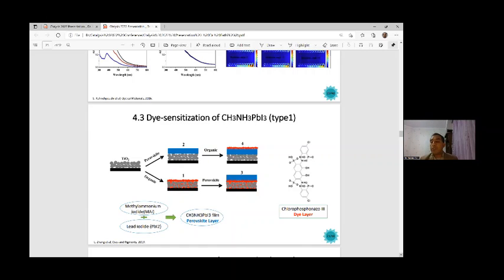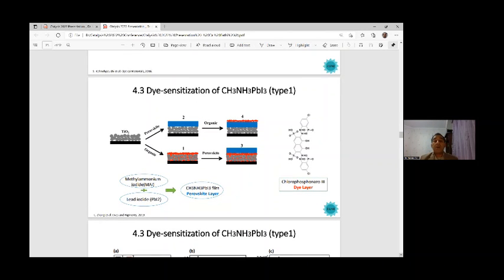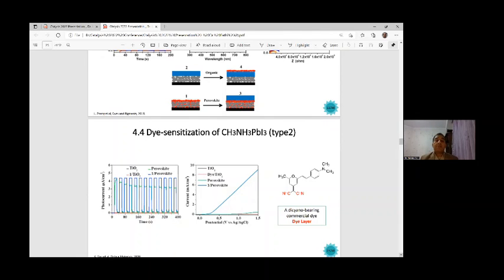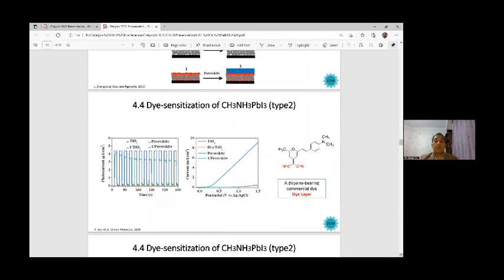However, in direct contact with an aqueous solution, they show poor performance. Here, using CH3NH3PbI3 halide perovskite and dye, we can improve system performance even in direct contact with aqueous solution. We have sensitized the halide perovskite structure with a dye structure in order to overcome the issue of interaction between the perovskite structure and the aqueous environment. At the next stage, you can see the type 2 structure of dye sensitization of halide perovskite structure. You can see the difference between the two structure types.